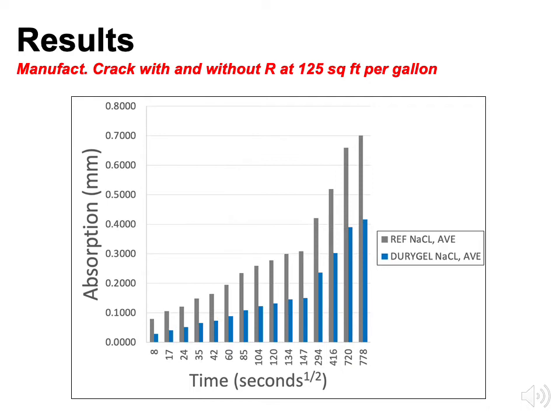our technical data sheets. We also ran these tests using simulated cement pore solutions, and saw a similar effect where the reference was actually drawing in water. And that's what those salts do, they have a capacity to imbibe water. But with the Durygel, even though there is a certain drawing in of water to create the hydrogel, we are creating that bridging of the concrete cracks that reduces the tendency for that concrete crack to imbibe water.